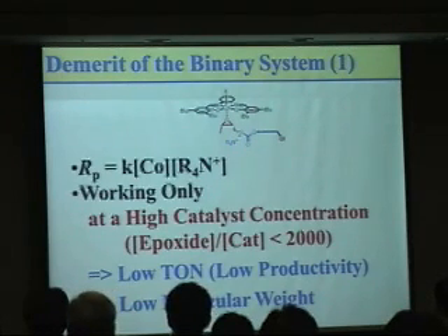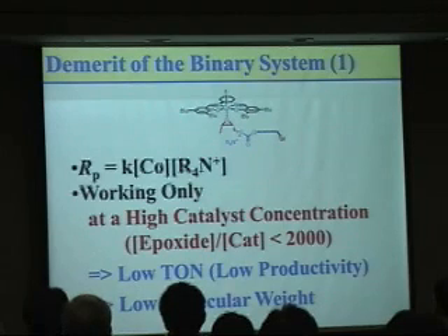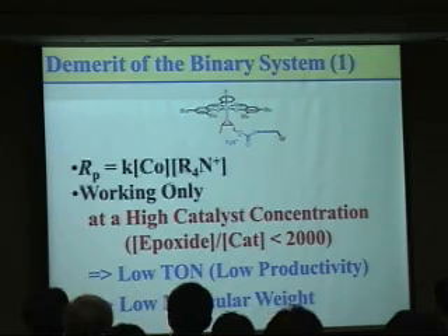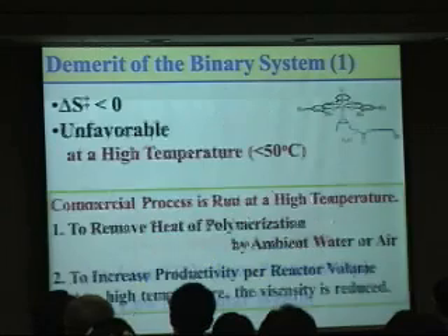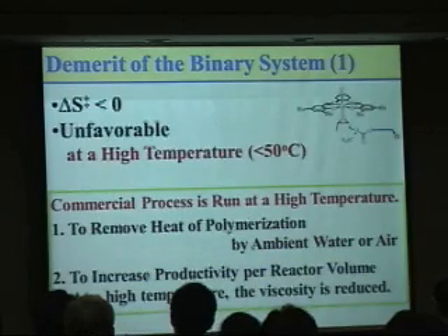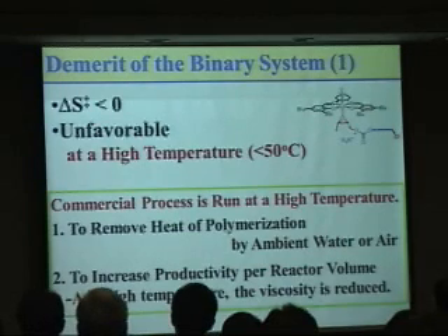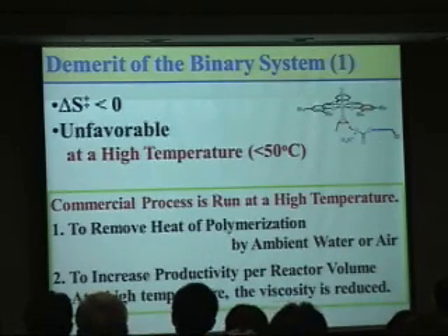And this polymerization shows the living character. The molecular weight is governed by the attained turnover number. Due to the low turnover number, a low molecular weight polymer is obtained, hampering the finding of applications. And under this propagation mechanism, delta S should be negative, and the polymerization reaction is unfavorable at a high temperature. The polymerization activity was realized below 50 degrees.